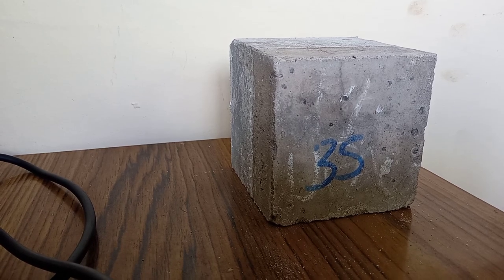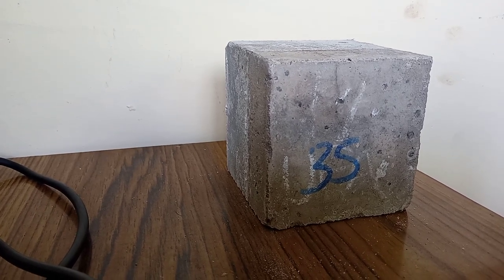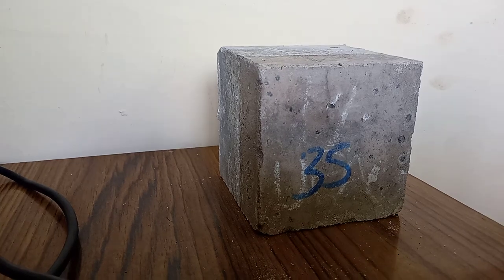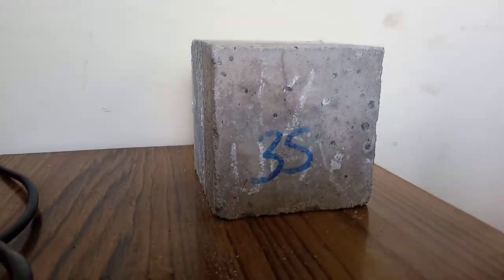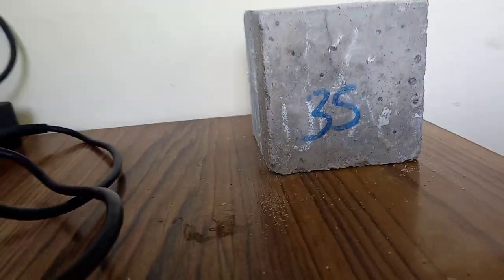Also, the lesser density of SCBA particles attributed to the 64% lower thermal coefficient, which confirmed the better thermal insulation and higher energy efficient capacity in the biomass replaced geopolymer concrete.